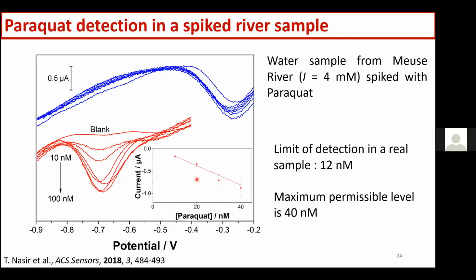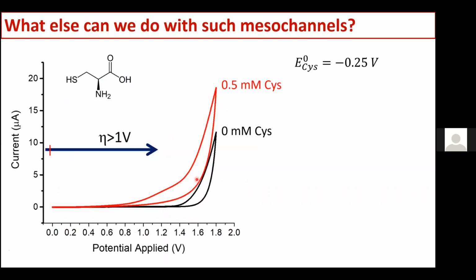So this is an example of what could be reached in terms of sensitivity with these mesoporous silica electrodes. I'm going to talk briefly, I guess I still have some time, about how we can introduce some selectivity to our systems by looking at the electrochemistry of cysteine. Cysteine is an amino acid that has a thiol group, here is the chemical structure, and you can oxidize it. If you look in the literature, the standard potential of cysteine is about minus 0.25 volts. But if you try to do this at an electrode, you have an overpotential that is greater than 1 volt. Here you see the oxidation of cysteine is at about 1.1 volt or so, and it's not a very well defined signal.